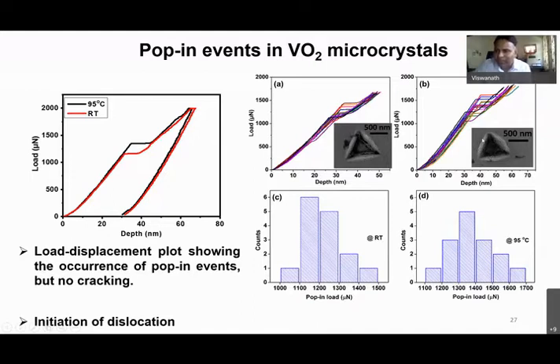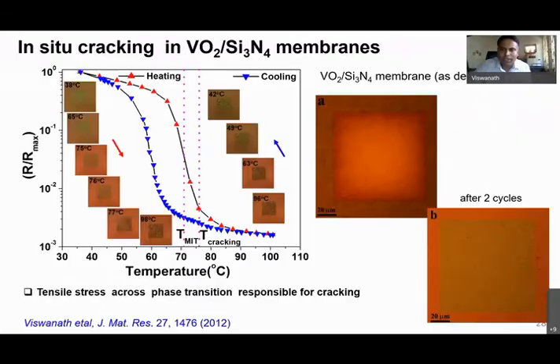We could not locate clearly any shear bands and so on, but some slip band kind of structures are seen in AFM and SEM. So we do think it is maybe due to the dislocation initiation. At the same time, the fracture cannot be completely ruled out. In order to capture that, we thought we can probably increase the load.